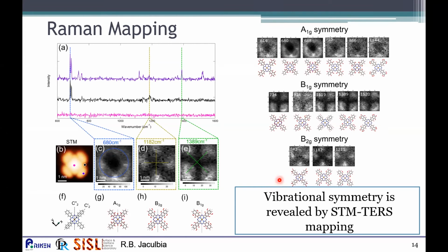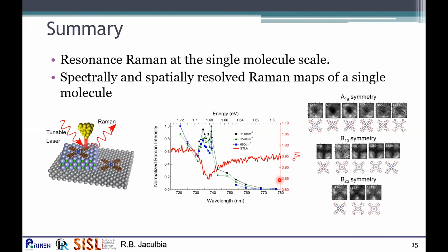So in summary, we have observed resonance Raman spectroscopy at the single molecule scale, and we have spectrally and spatially resolved Raman maps of a single molecule, which revealed that the vibrational symmetry governs the patterns of the Raman maps.